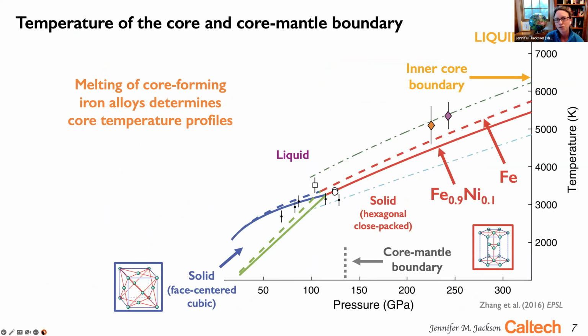Okay, so turning first to the thermal constraints of Earth's core, here we show a phase diagram of iron, an iron alloyed with 10% nickel. The solidus or melting of core-forming alloys at the boundary between Earth's solid core and liquid core thus determines the core temperatures. So it is known that there should be light elements in Earth's core due to the density deficit observed geophysically between that of an iron nickel alloy and that again of the geophysical constraints.